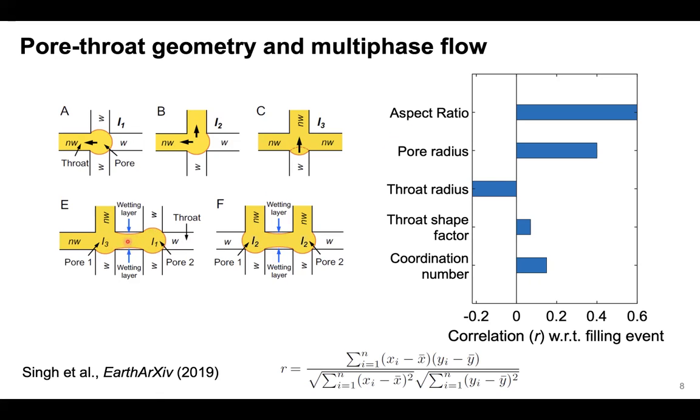Now, we did this correlation analysis on the whole data set. If we got 0 value, that means it's not dependent, not correlated. But if it's -1 or 1, it has some dependence or correlation with the pore-throat geometry. If you see all the parameters, this aspect ratio quickly outshines, and it's clearly correlated very well, not fully, but very well, to the pore-throat space.